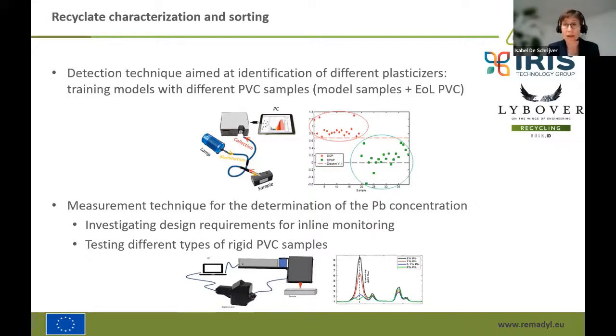And then we work together with the partners mentioned here, so with Iris and Lybover, on two different methods. So the first method is, of course, the identification of the plasticizers, where, of course, we started with model samples, but we are now also looking at end-of-life PVC streams, trying to separate depending on the type of plasticizer being used, because, of course, not all plasticizers are bad. And you see here on the picture a nice example where we were able to separate a DOP plasticizer from a DPHP plasticizer. So this would help, of course, to have a first separation of your base material.